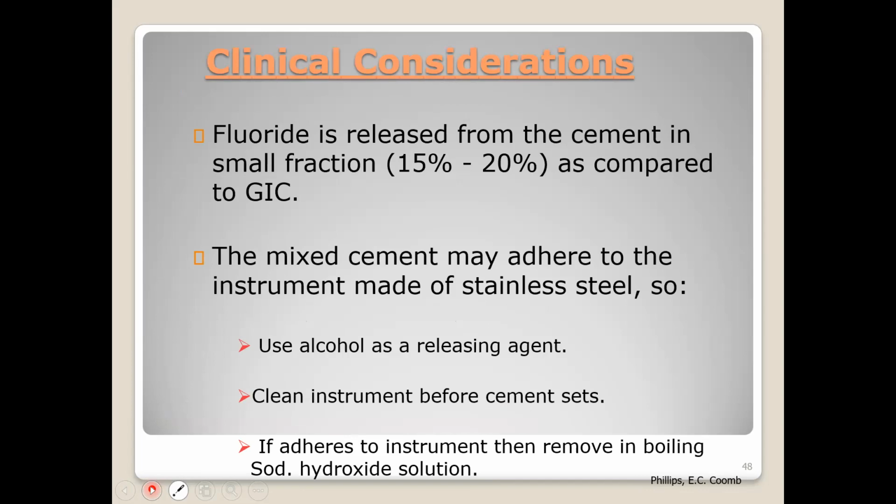The mixed cement may adhere to these instruments made of stainless steel. So use your alcohol as a releasing agent. Clean instruments before the cement sets. If it adheres to the instrument, then remove it in boiling sodium hydroxide solution.